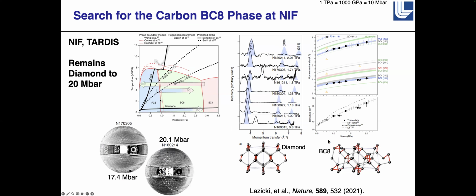And so what we've been doing with Ivan is triple shock experiments where we try to get into the range at about 20 megabars where the diamond should melt, and it should be very easy to melt the diamond, and then the liquid will rapidly refreeze. In the simulations, it refreezes within picoseconds. And then there's also Dominik Kraus at the University of Rostock in Germany. He's been doing a lot of experiments on X-FELs where he takes plastics, like just plastic CH, and double shocks it and forms diamond from that.